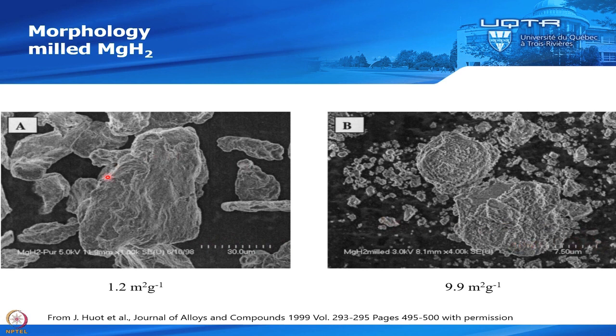So you see that before milling, the particles are smooth, the surface is smooth. But after milling, the particles are smaller, because this is only 7.5 micron, but these are the big ones, and I have smaller ones here. So you have a strong reduction of particle size. And also, for example, this particle is an agglomeration of smaller particles. So sometimes by ball milling, you will break particles, but you will also tend to fuse particles together.